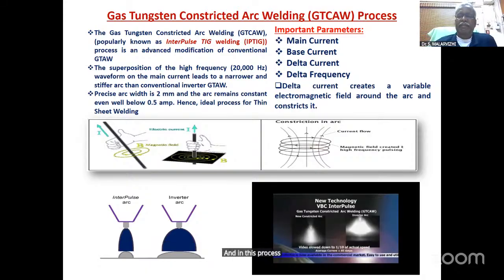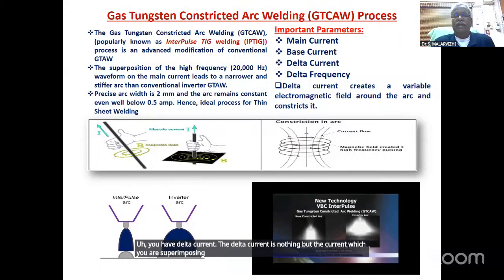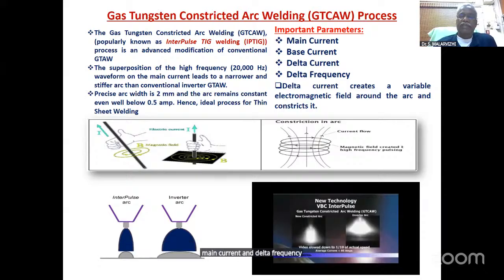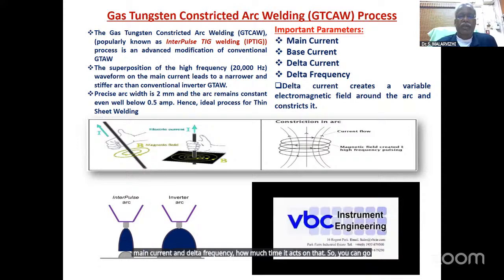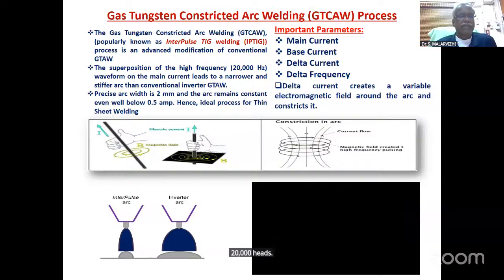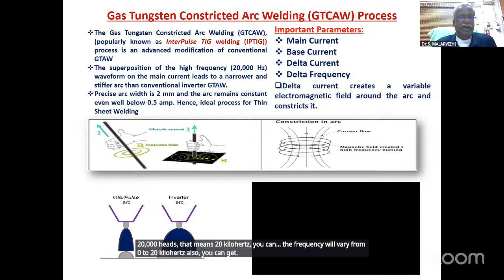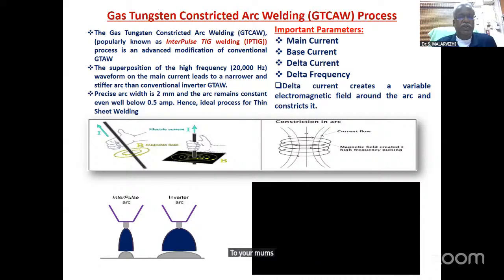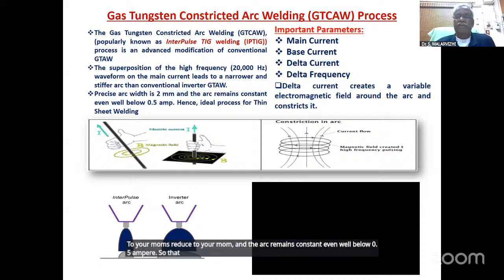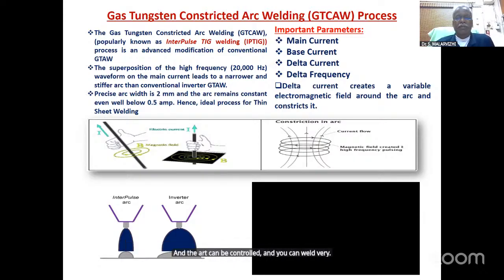In this process, the main parameters are, apart from the main current and the base current, the delta current. The delta current is the current which you superimpose on the original main current, and the delta frequency, how much time it acts. You can go up to 20,000 hertz, that means 20 kilohertz; the frequency will vary from 0 to 20 kilohertz. By doing that, the arc width is reduced to 2 mm, and the arc remains constant even well below 0.5 ampere. That is the advantage of this process. Even at low current the arc can be controlled, and you can weld very, very thin sheets with minimum heat input.